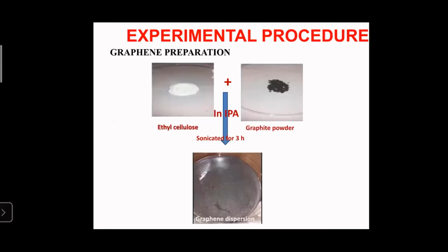Directly to the experimental procedure, we just mixed ethyl cellulose and graphite in a specific ratio in isopropyl alcohol solution. The mixture is sonicated for 3 hours in a bath sonicator. We got a stable graphene dispersion. The unexfoliated graphite is separated. By using exfoliating agents, normally we are getting a highly concentrated graphene solution. It is just graphene dispersion.